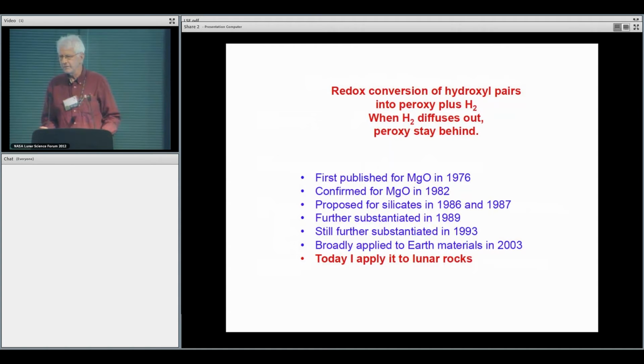And the next slide just shows you a little bit of whining from my side, because I've been working on this for a good 35 years, and we have essentially thrown every technique that is available on the books at studying these peroxy defects, first in magnesium oxide, and then in minerals and in glasses. We were able to show consistently that in magnesium oxide, the 1-to-1 stoichiometry is not followed. It deviates because of this formation, and it was then substantiated and broadly applied to earth minerals in a sequence of papers that appeared until about 5 or 10 years ago.